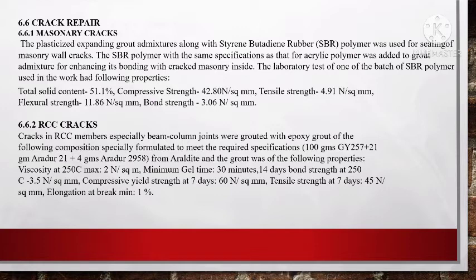The laboratory test of one of the batches of SBR polymer used in the work had the following properties. Total solid content is 51.1%, compressive strength is 42.80 Newton per square mm, tensile strength is 4.91 Newton per square mm, flexural strength is 11.86 Newton per square mm, bond strength is 3.06 Newton per square mm. Second is the RCC crack.